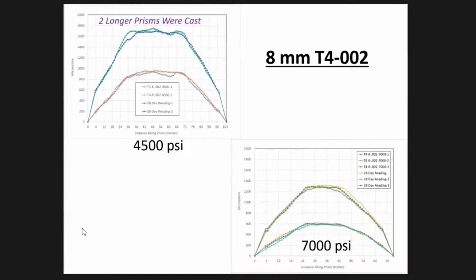And so we're determining transfer length for both. At 28 days, our strain values, these are compressive strains, grow quite a bit. And that's due to creep and shrinkage, because that concrete keeps getting shorter over time.